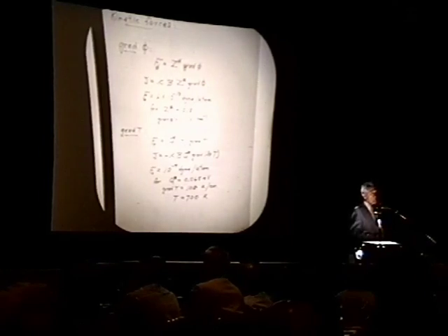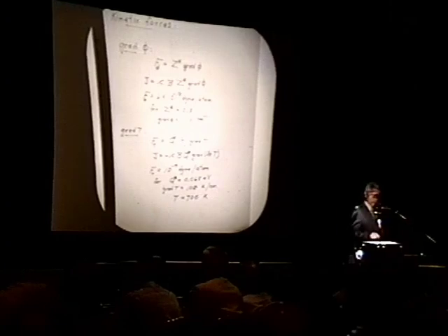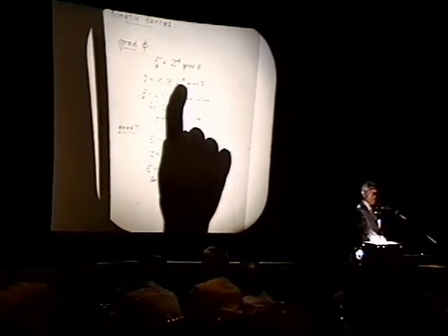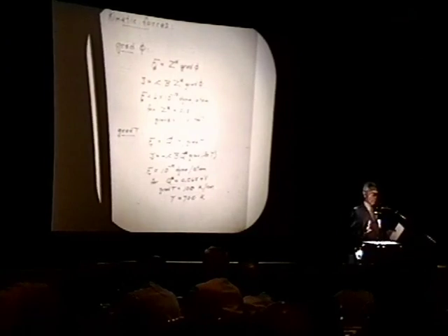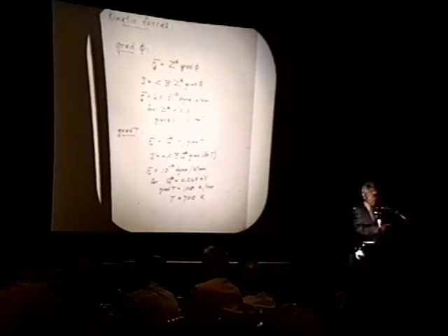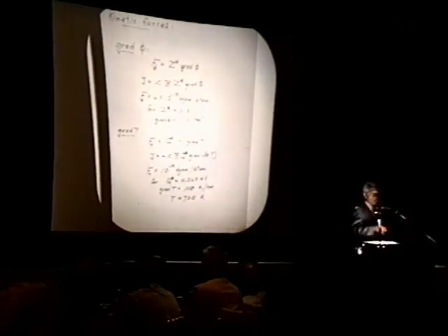You must not infer from that that the ionicity of the hydrogen dissolved is 0.6, because what's happening is that this thing responds not only to the electron, but also to momentum transfer between the flux of electrons and holes, one direction, the other direction, and the dissolved species in its activated state as it's jumping from place to place. I don't want to say more about that because I lack time.